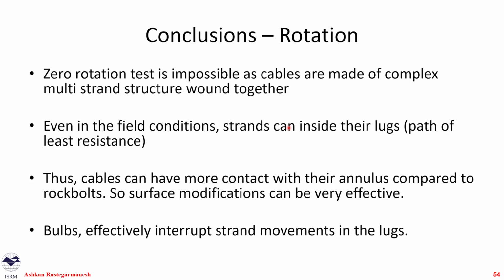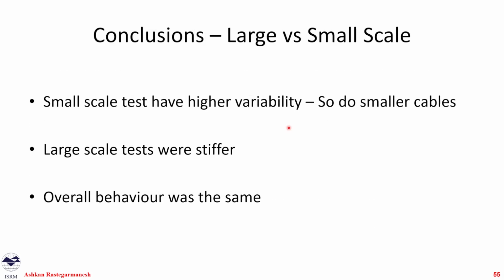Bulbs basically interrupt the strand movement in the lugs, so they are like big, chunky, unwieldy structures that we have there. And we can actually use this to design cable bolts with bulb locations and surface patterns to come up with some very interesting ideas. The difference between large and small scale tests is that smaller scale tests have difficulties with repeatability, so they have higher variability, and so do some smaller cables. And larger scale tests have a stiffer behavior, so you have a steeper load pickup line, and overall behavior, but at the end it is the same.